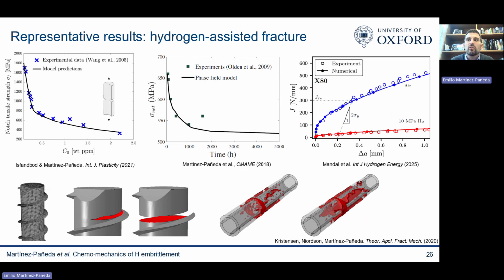We've been using these models for quite some time now, and we've been able to show that they are able to capture very well experiments. You see an example here. Symbols are experimental data points. You see examples here with high-strength steels, duplex stainless steels, pipeline materials.